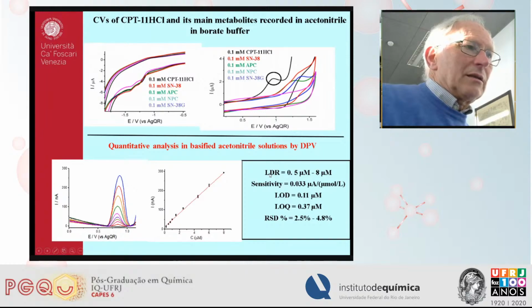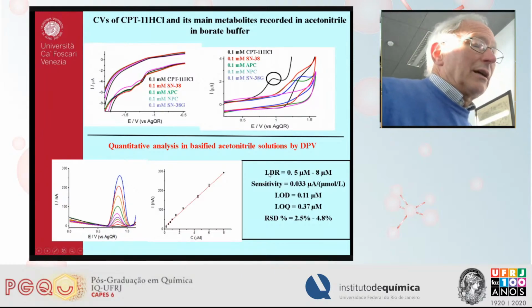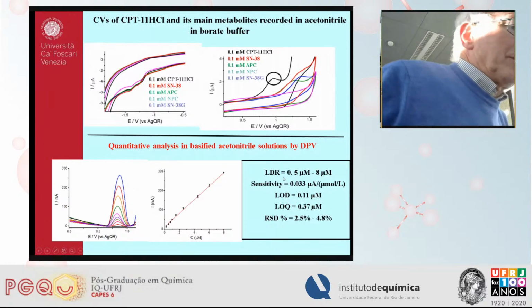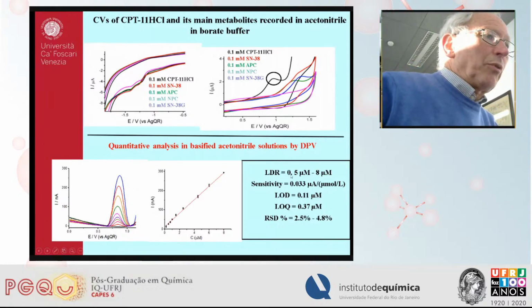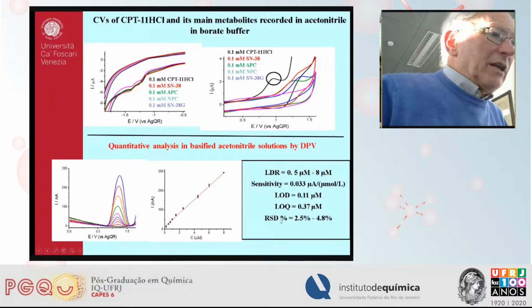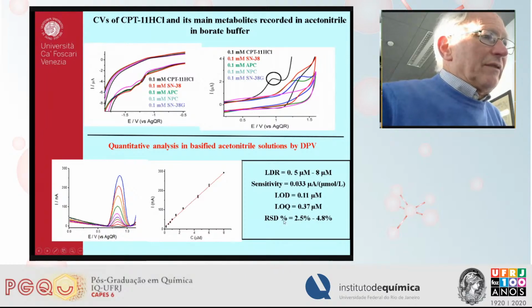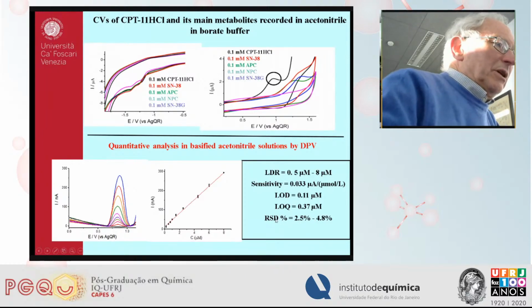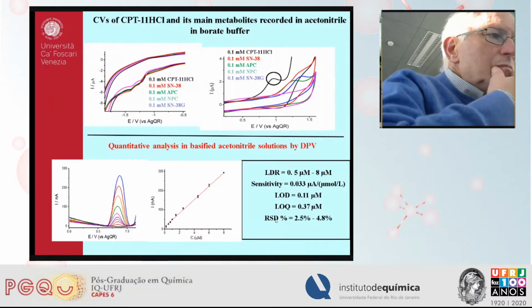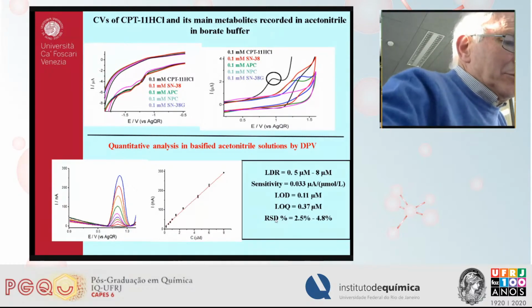The linear range of the measurement varied between 0.5 micromolar and 8 micromolar. Sensitivity was quite good. The detection limit was 0.11 micromolar. The quantification limit was 0.37 micromolar. Reproducibility, as shown here, is very, very good. But this kind of results were obtained in synthetic media.